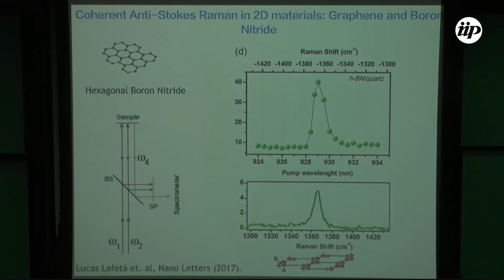So we start by doing this coherent anti-Stokes Raman in boron nitride. We exfoliated boron nitride samples on a quartz substrate. And here's the four-wave mixing signal as a function of the pump wavelength. You see that you have some four-wave mixing signal intensity, but when you tune the pump wavelength to around 929, you have an increase in the four-wave mixing signal intensity. If you convert this pump wavelength to the Raman shift, that is the energy difference between the two lasers, you see that the resonance occurs around 1360 wave numbers. In a normal Raman, this corresponds to the Raman band of boron nitride, the vibration of the boron and nitrogen against each other.